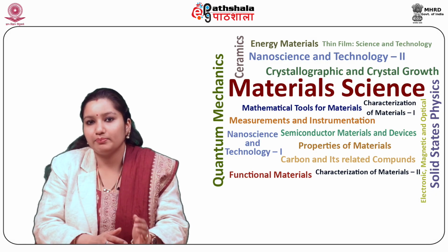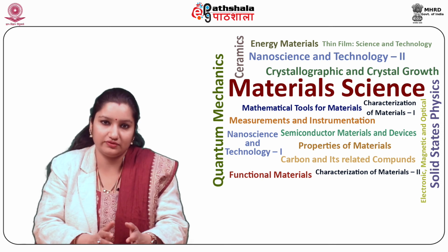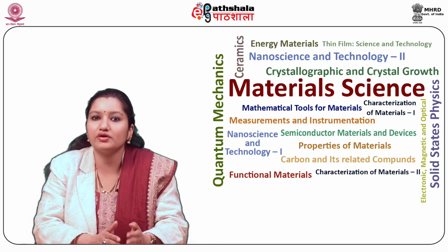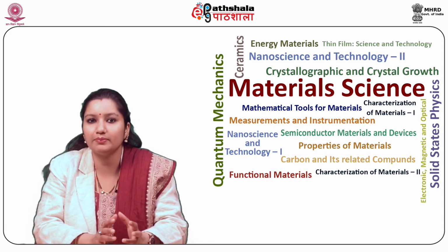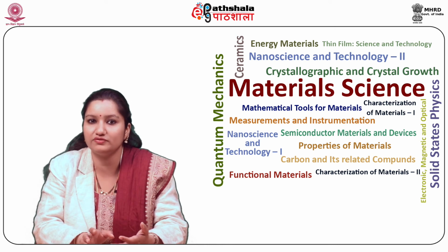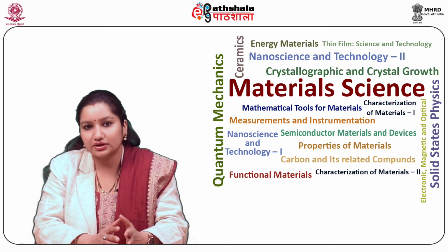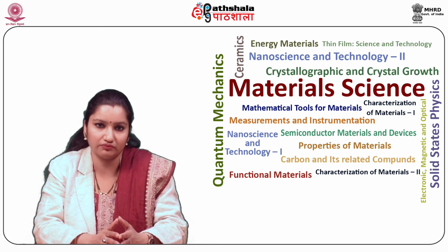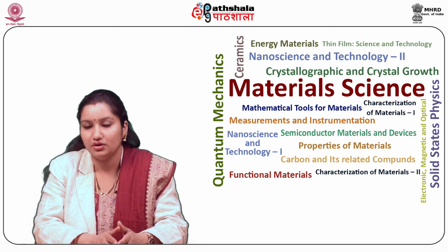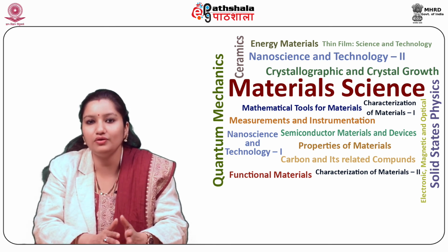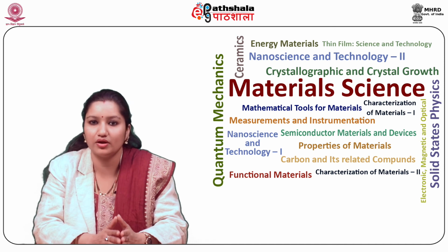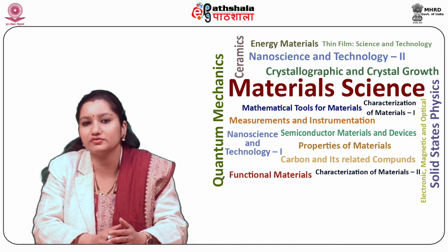This oscillatory nature implies that some spatial frequencies are faithfully imaged by the microscope, while others are suppressed. By combining multiple images with different spatial frequencies, techniques such as focal series reconstruction can be used to improve the resolution of the TEM in a limited manner. The contrast transfer function can to some extent be experimentally approximated through techniques such as Fourier transforming images of amorphous material such as amorphous carbon.